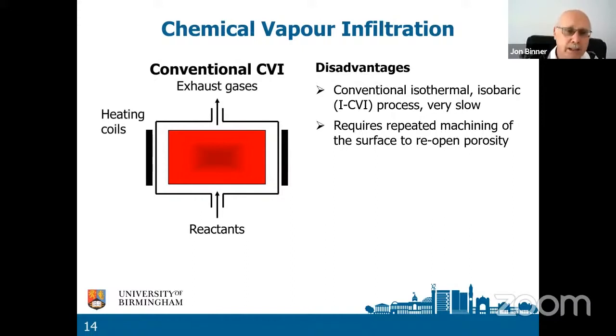Why is it slow? Well, if you look at the little diagram, hopefully you can see that the sample is the thing that's red, and the color of the red is deeper in the middle. In other words, it is hottest at the surface and it is coolest in the middle. So when you pass your gases through, the gases tend to break down and deposit on the surface. And this blocks off the channels, the pores that lead the gases to the center of the body. So after a number of hours of processing, you stop the process, you take the part out, all the parts out, you machine the surface, then you put the parts back in, then you reheat the whole thing. Heating has to be very slow because we want to minimize temperature gradients, and then you go through the whole process again. And you might have to do the machining stage 2 or 3 times. And so the whole process can easily take 1,000 hours or about 3 months.